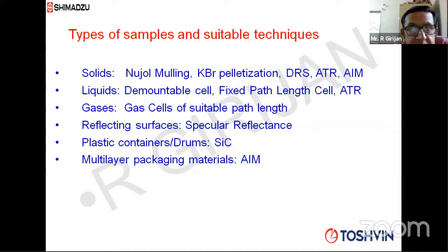After that time, you release the vacuum, release the pressure, open the die, and if you have prepared it properly, you will get a 13 millimeter diameter circular disc, which looks like a piece of glass. This process is known as the KBr pelletization method. At the same time, it is a very difficult process, because it is highly subjective. Different people making a pellet of the same sample, the quality of the pellet can be different depending upon the individual. It's a very, very difficult, time consuming process. And that was a process widely employed in the pharmaceutical industry till very recently.